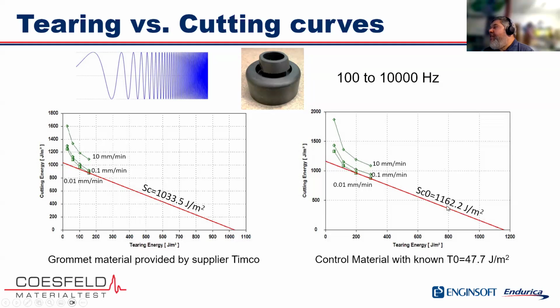And we measure the cutting energy as 1162. For the grommet material, we measure a cutting energy of 1033. And so the fatigue threshold that we would measure or report then would be basically 47.7 times the ratio of 1033 divided by 1162. That's going to give us the fatigue threshold for the grommet material.